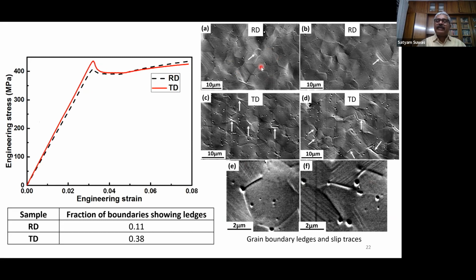And to our surprise, when we examined the deformed microstructure, these were very well electropolished samples, and we did some profilometry and we could see differences. We could see the formation of ledges along the grain boundary. In the case of RD samples, the grain boundaries look very normal, while in the case of TD samples, we could see ledge formation. So this is also a function of the direction in which we have extracted the sample, and very clearly we could see that there is a substantial difference in the grain boundary fraction consisting of ledges between RD and TD samples.